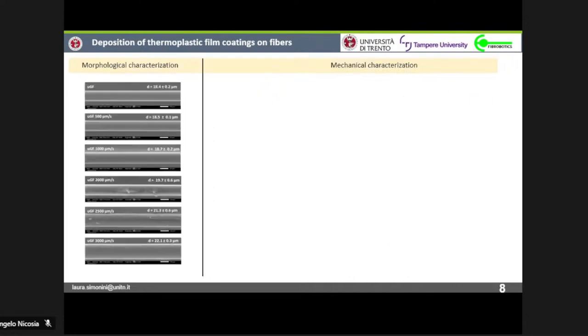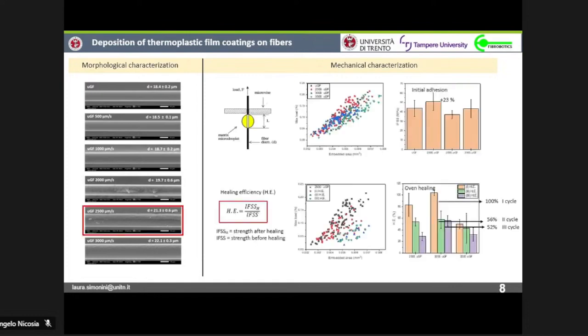From the morphological characterization, we can see that the deposition of this layer is very homogeneous, very compact, and also consistent. We can see that there is a relation between the coating speed and the thickness of this coating. From this analysis, we selected just one combination, the best that we supposed. Then we did the mechanical characterization. We applied the microdebonding test for the calculation of the interfacial shear strength. From this test, we obtain a huge amount of data that are reported here.